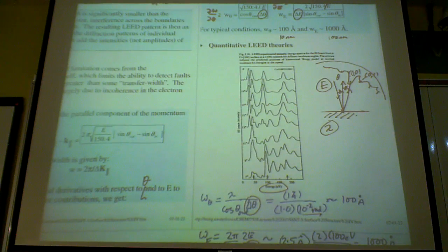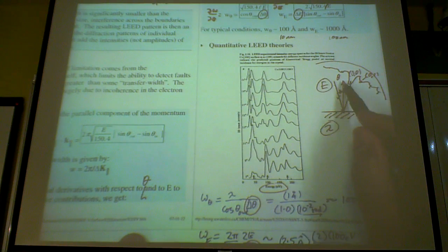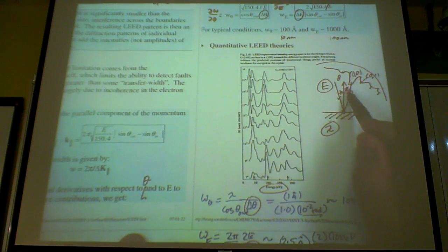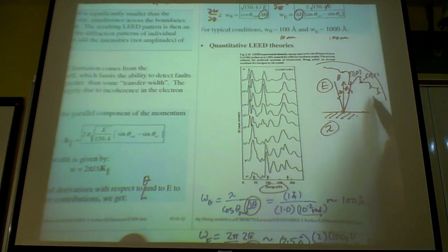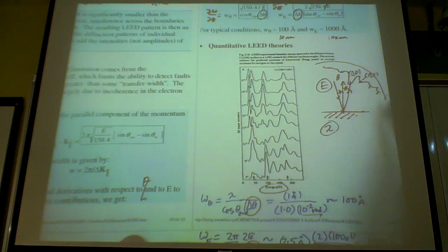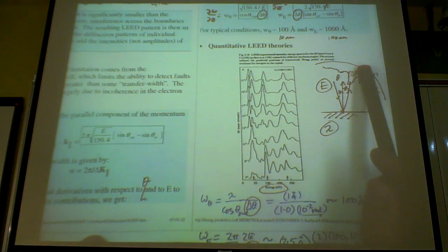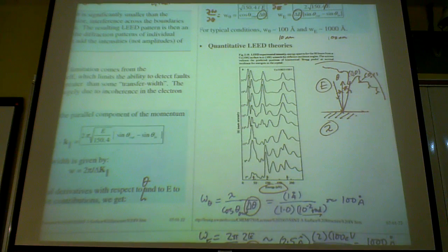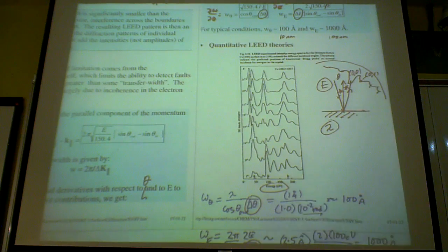So you can think of it as this is backward scattering, this beam coming back. These are the little angles that I see. So this corresponds to 9 degrees, 11 degrees, 13 degrees, and so forth. And again, I put my detector here, and then I change the kinetic energy of the incoming electron beam. I sample the intensity, right?